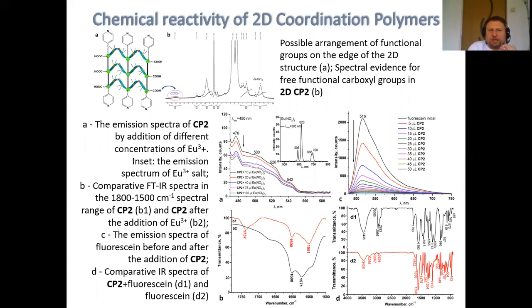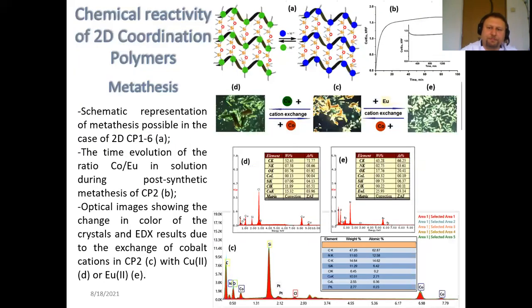The functional groups on the edges of the two-dimensional coordination network show chemical reactivity with a possible arrangement of free functional carboxyl groups at the edge of the two-dimensional layer. The analysis by fluorescence and infrared spectroscopy demonstrated the complexation by the free carboxylate groups of other metal ions, such as europium. The coordination polymers have shown clear salt metathesis reaction with the possibility to exchange cations, such as cobalt with copper or cobalt with europium.